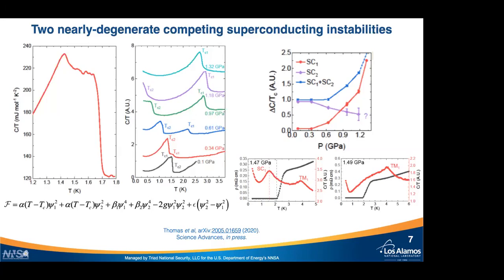It's interesting that when that state comes up, TM1, the superconducting transition from the bulk heat capacity measurement, starts to broaden first, and it's at lower temperatures than the onset or offset even of the zero resistance state. So this tells us that these two states are competing with each other very dramatically, and this indicates that there is no microscopic coexistence of these two states. The figure here on the right is at slightly higher pressures, showing that the superconducting bulk transition disappears very abruptly indeed. That's likely why the previous results could not see this evolution of the bulk superconducting transition.